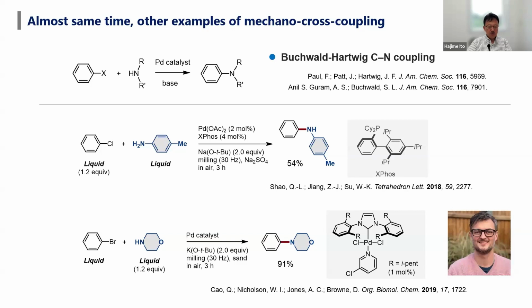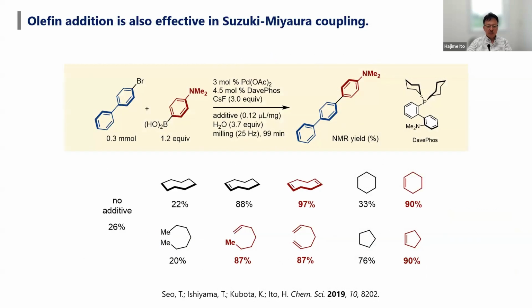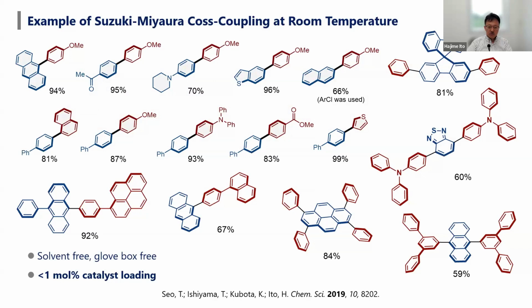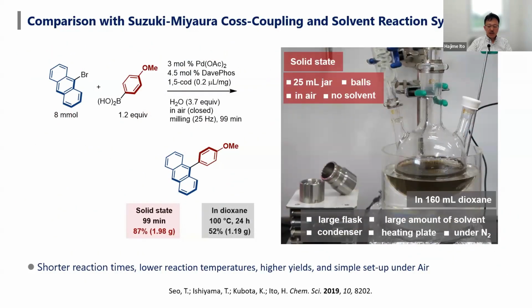But they reported their examples using only liquid materials, whereas our Suzuki cross-coupling reaction focused more on solid materials. We also found that addition of 1,5-COD can improve this reactivity very much, and here are some examples. I would like to show this slide to convince you that mechanochemistry is more efficient compared to conventional solution phase reactions.